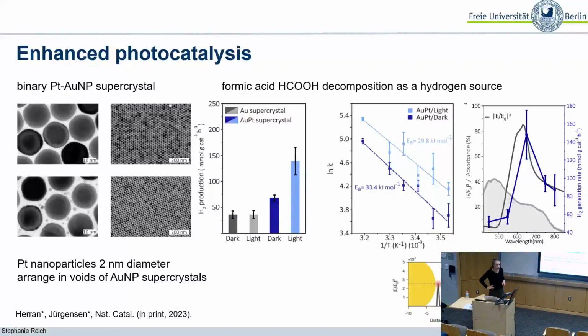Yeah, so I saw in your work that you use really large gold particles. And I was going to ask about the length of the polymer. You said it's about 2 nanometers. But that can be varied, and then the distance between the gold nanoparticles will change. So if you use really small gold particles in the same structure, is that going to affect your coupling effect?